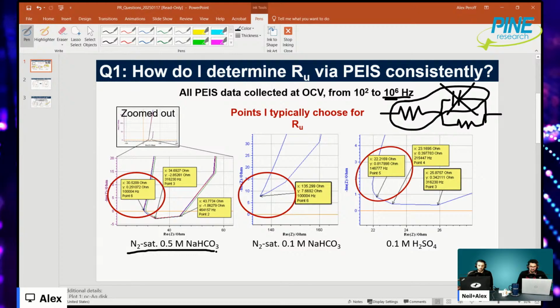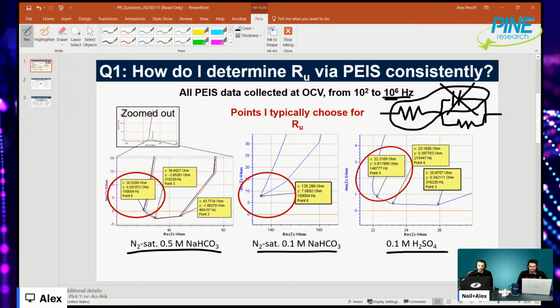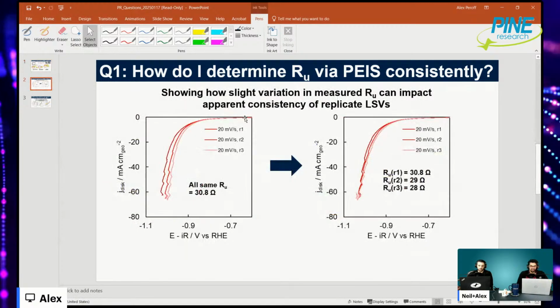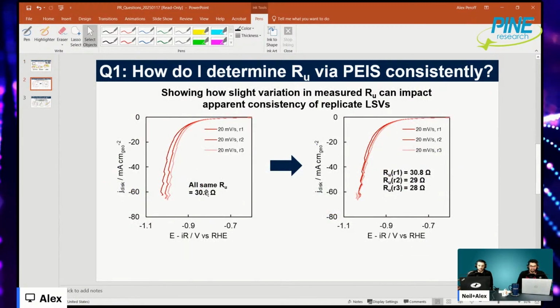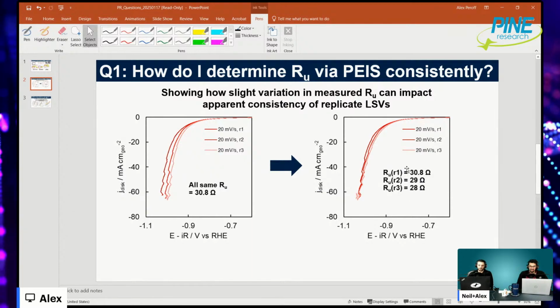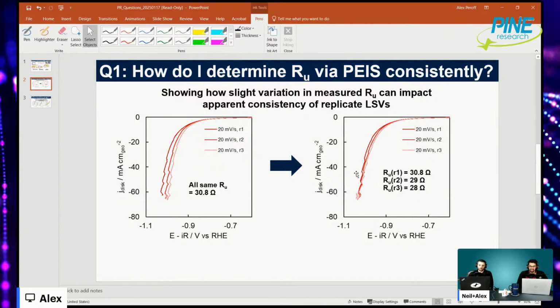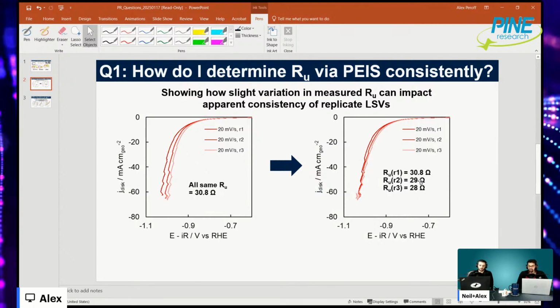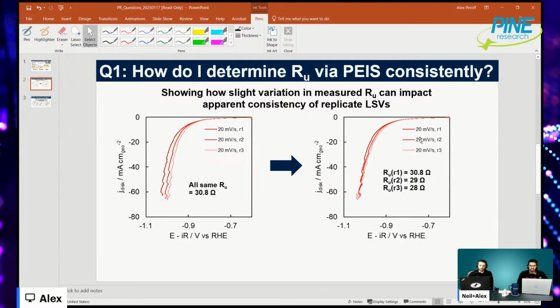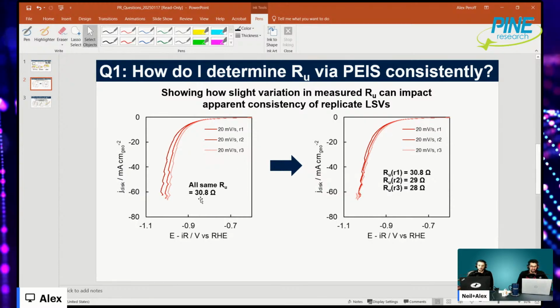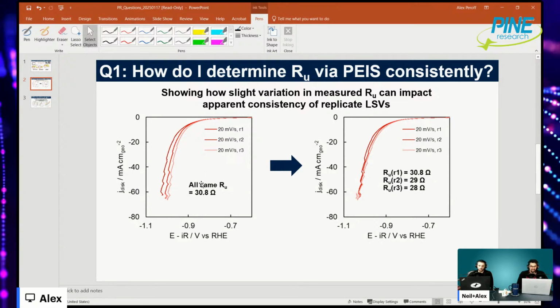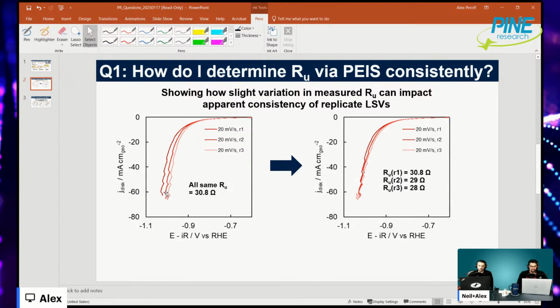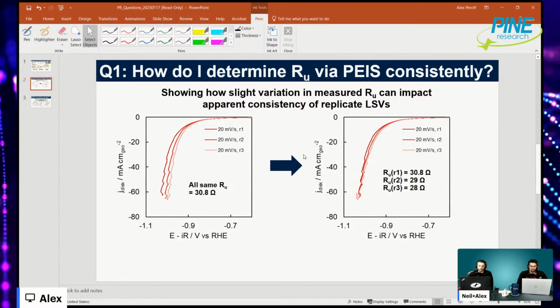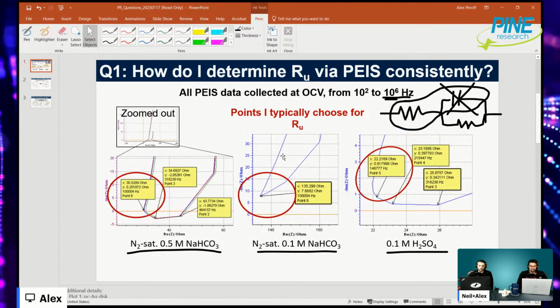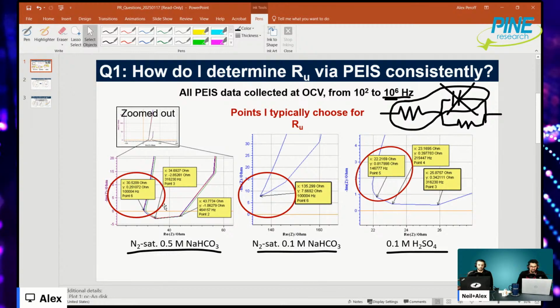And this person is using different solutions, and they have found that even under slight variations, this is where they do the LSV, and they find slight variations like 1-2 ohms, maybe 3 at most. This is consistent, but when they just pick one value, you actually end up getting fairly significant shifts in the solution resistance. So they're trying to figure out what exactly is the best way to determine the resistance.